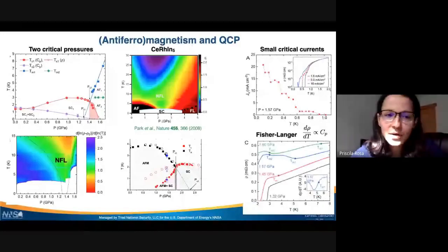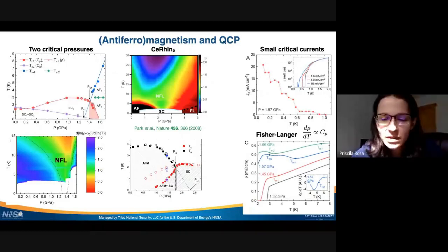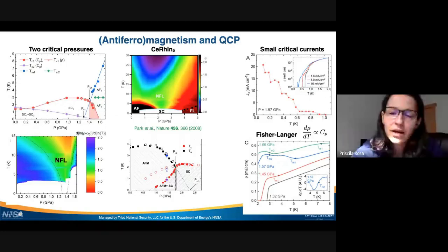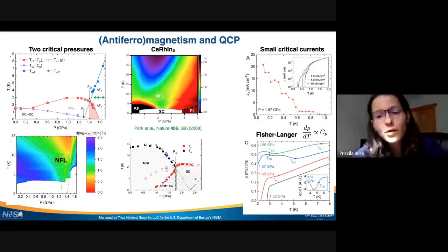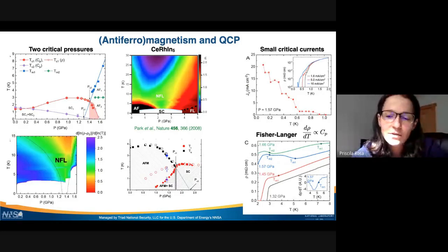And another point that I wanted to make about the magnetism at higher pressures is that often we have the Fisher-Langer relationship that tells us that the derivative of the resistance will be proportional to the heat capacity jump. And because the heat capacity jump is always positive, you always have the resistance going down on cooling through a magnetic transition. But that's not the case. That's always the case for ferromagnetic systems, but not necessarily for antiferromagnetic systems, because you can have things, for example, like a superzone gap, when the wave vector of the magnetic structure is not commensurate with the crystal structure. So all of this is telling us that this material is actually close by to an antiferromagnetic QCP.